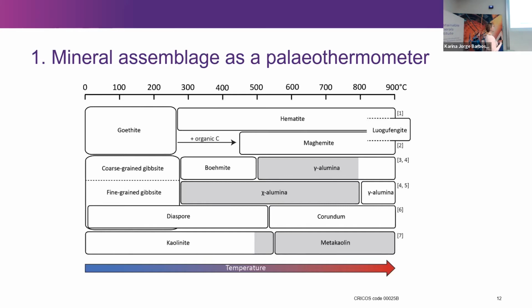If we have gibbsite in our starting mix, depending on the grain size of the gibbsite, we produce a variety of these different transition aluminas. We can make corundum at quite low temperatures if there's diaspore, which is just another aluminium hydroxide phase. And when we have kaolinite in the mix, we can get metakaolin at about 550 degrees. The boxes shaded in gray just indicate ones that are X-ray amorphous, so they're not actually detected in X-ray diffraction. So if you do have these phases forming, then you might see an increase in poorly diffracting material in your mineralogy and be able to identify it that way.